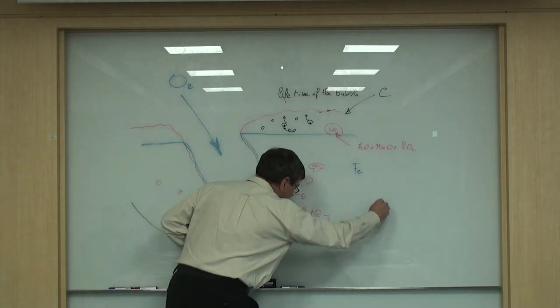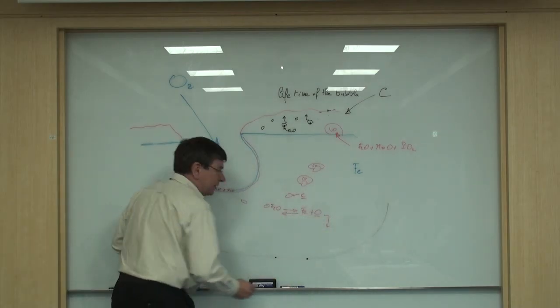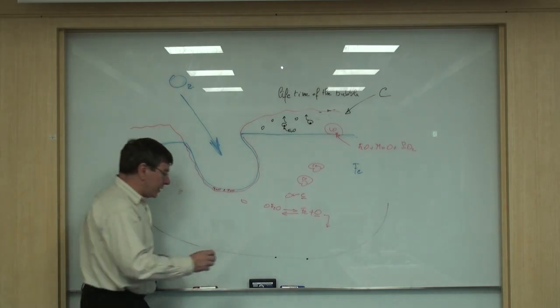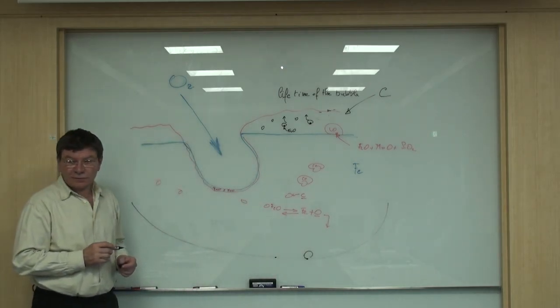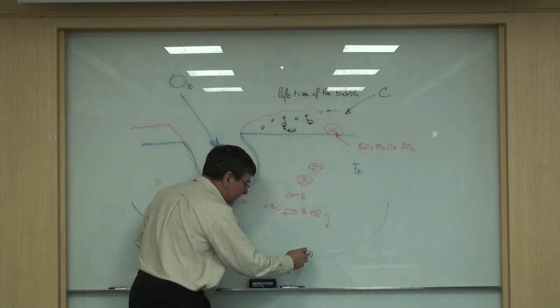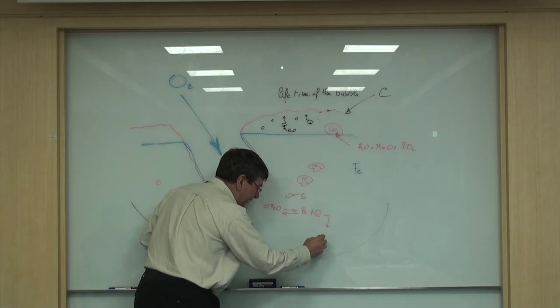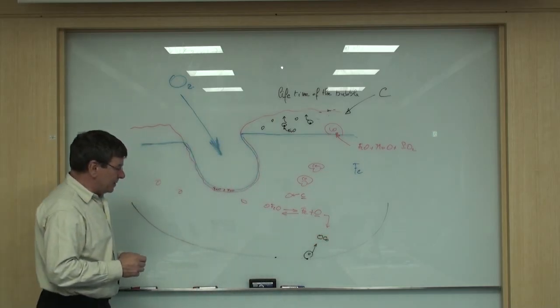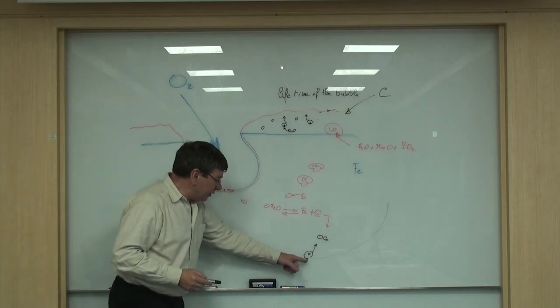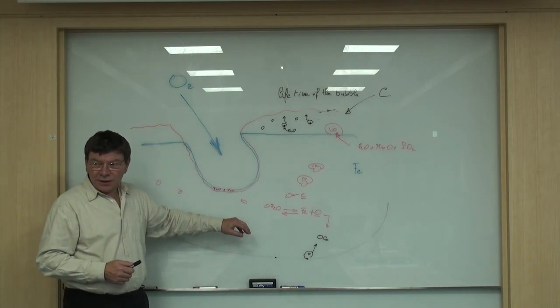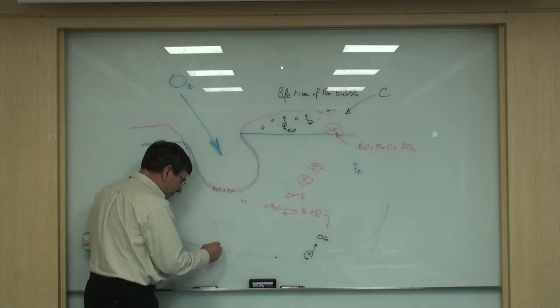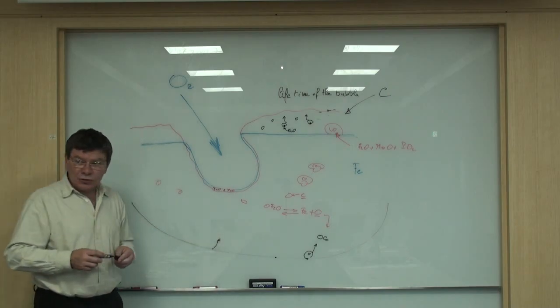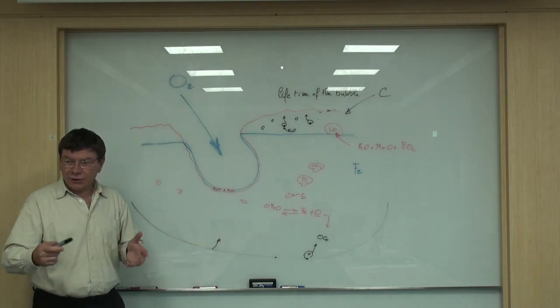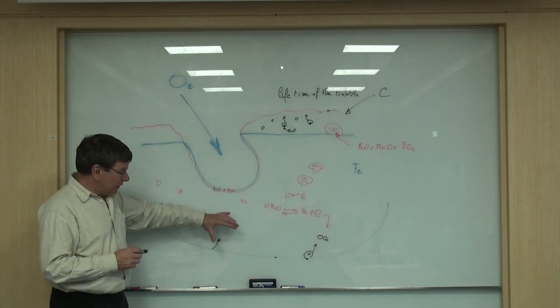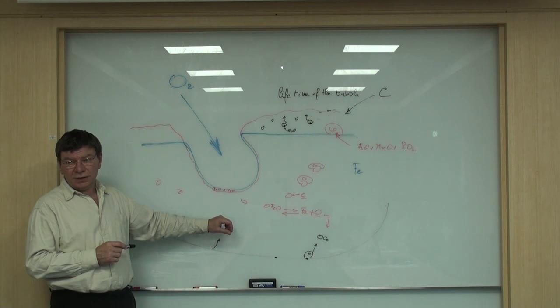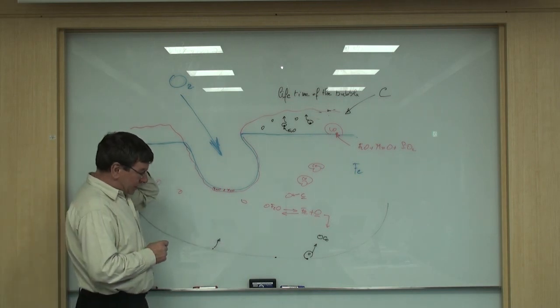You have the refractory lining, and you have sites on the bottom of the refractory where you generate small bubbles. Originally it's oxygen, and it reacts with carbon, and you have CO bubbles. This originates on the bottom or on impurities in the steel, because you may have particles of refractory getting up, or inclusions of oxides in the steel, such as Al2O3 or some very small particles, generating these sites where you can initiate the decarburization.